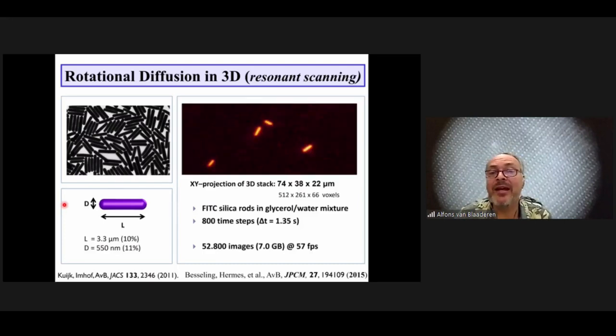And this movie that I'm playing here is actually a projected 3D data set. So we can get the free diffusion of these rod-like silica particles, the synthesis of which we developed about 10 years ago, and which can also be made fluorescent. These rod-like silica particles are described in this paper cited below. But the real space analysis is something that we developed in the last 5-6 years. So that movie was particles with motions in 3D.